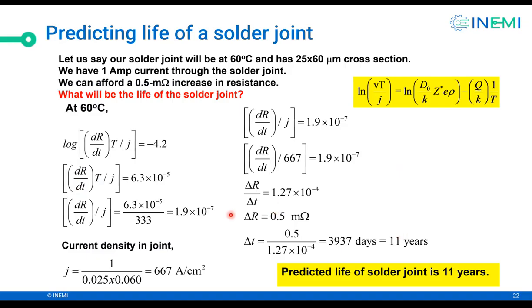So this chart basically shows how to predict the life of a solder joint. In this case, we are saying it is 11 years, when the temperature of the solder is 60 degrees. Here's the cross section of the solder joint. We're saying 1 amp current and 0.5 milliohms increase in resistance is the failure criteria. So this is simple math, and we conclude under these conditions, the life is 11 years.